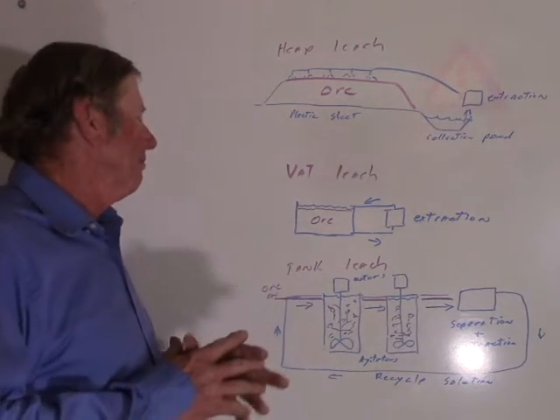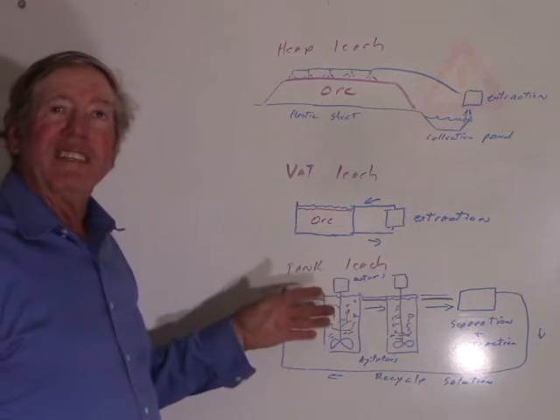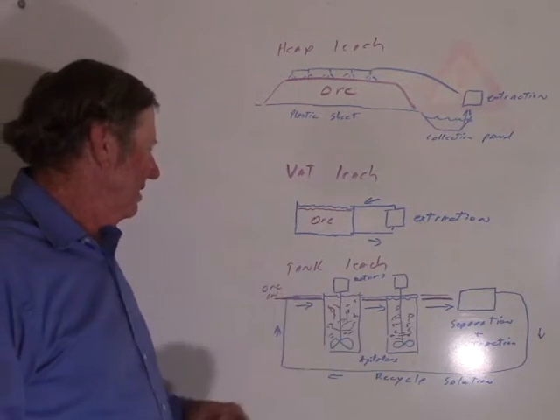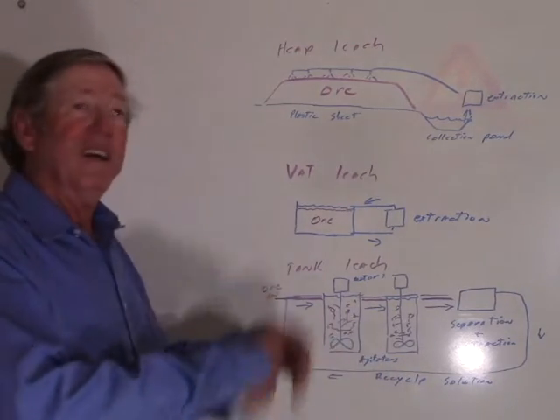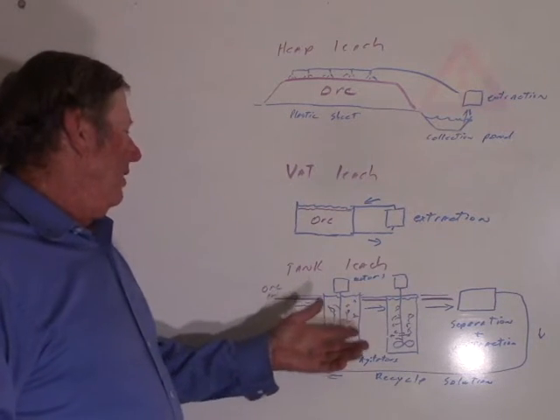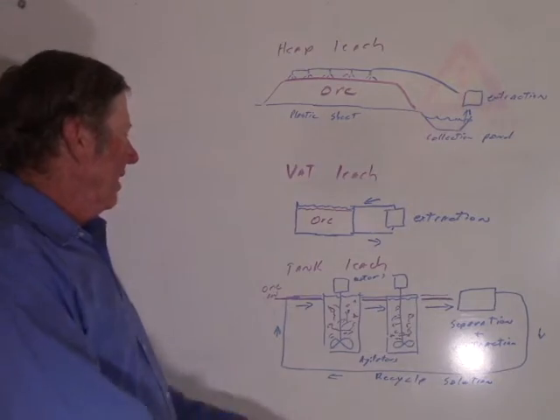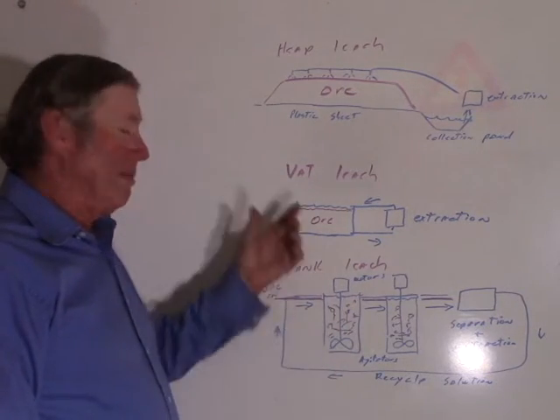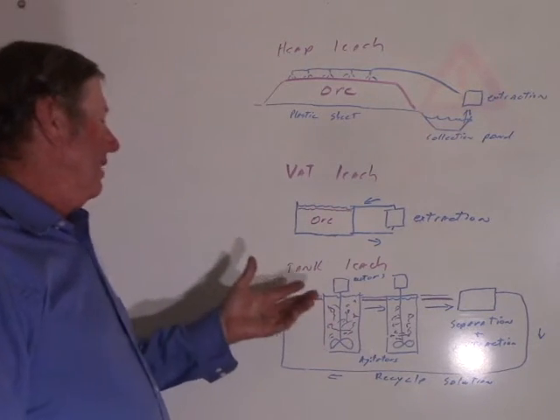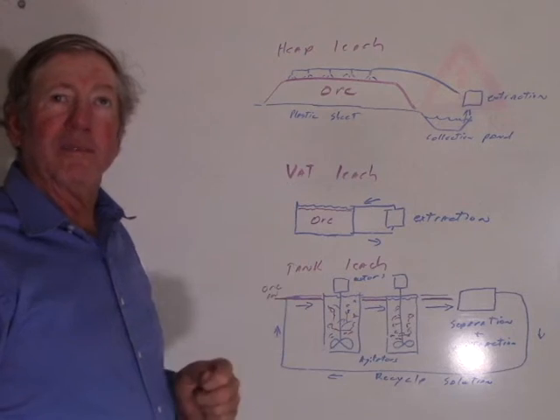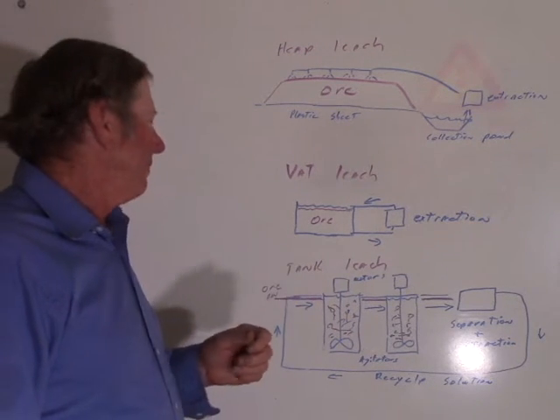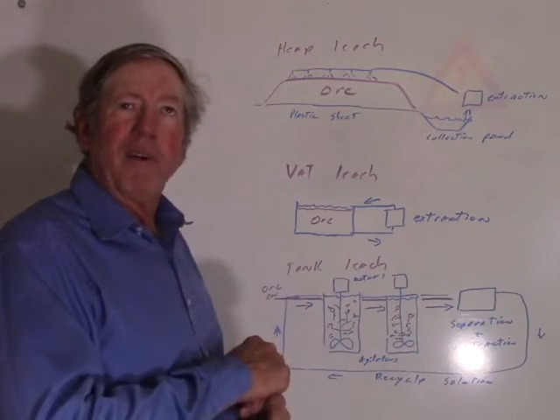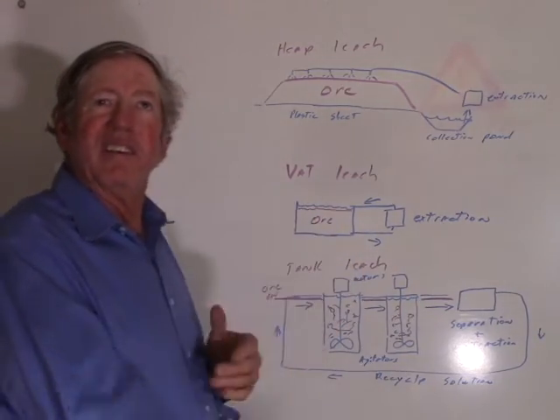The most efficient is what's known as an agitated tank leach. You have tanks with some form of agitation — agitators, impellers, big propellers at the bottom that stir things up. You can put an air pipe down there, inject air, and it brings things up to the top using what's known as an air dredge — that would be a pachuca tank. The advantage of a pachuca tank is also good aeration; oxygen is important to cyanide. By getting maximum flow of liquid over the particles, you have rock particles scrubbing any gold particles and grinding off any passivation layers that are forming.